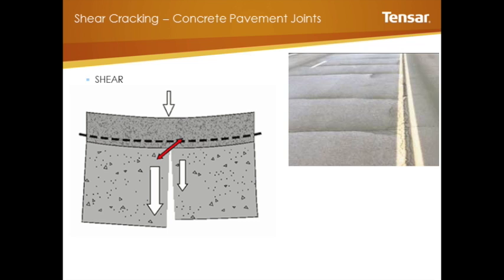Good. The next type of crack is a shear crack, and this one is best represented by composite pavements. So this is where you have your joints moving vertically under traffic loads, where your dowel bars are typically located, and you get a relative movement of the slab. So we talk about load transfer. If the two slabs are moving down completely in sync with one another, then we talk about 100% load transfer because there's no relative movement. And typically when the pavement structure is new, you would hope that you experience that condition.